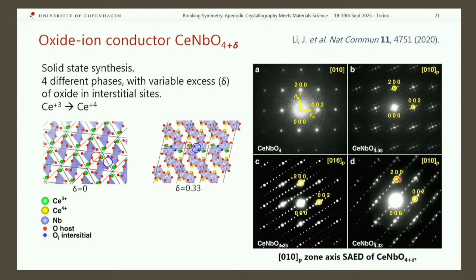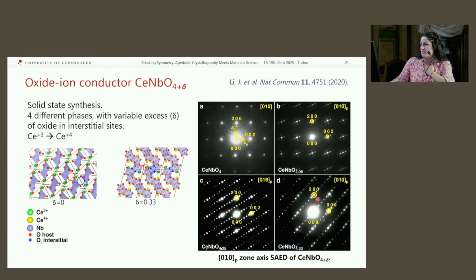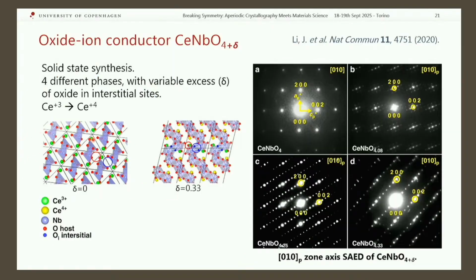So you see from the pattern, this is selected area electron diffraction, you see that there is an underlying square pattern common to all phases, but we have extra peaks here. So this is a superstructure of the basic non-doped cerium niobate. But it's commensurate, so it's an ordered structure. And this intermediate composition is a commensurate modulation. So not as interesting. So we can look at this other one with the very low amount of oxygen. We see that we have some weaker intensities around each peak.